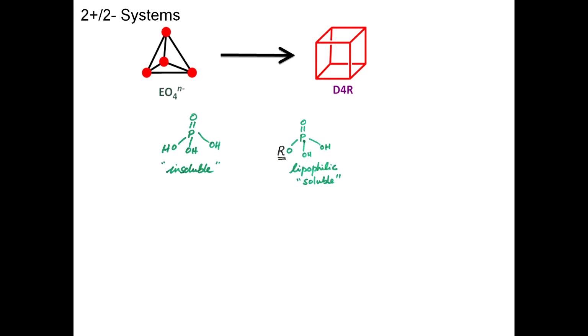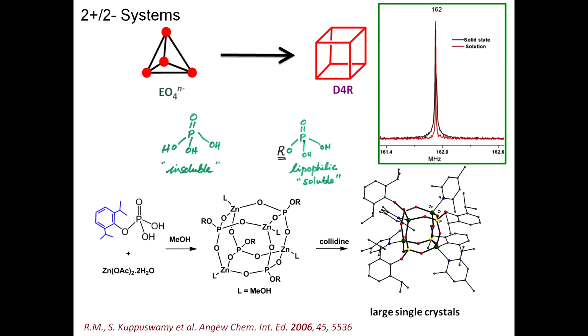So this is what I just talked about. In phosphoric acid, one hydrogen is replaced by an R group, which is insoluble in organic solvents. To make it soluble in organic solvents, I lipophilized it by putting in a 2,6-diisopropyl group. As one would expect, this molecule reacts with a divalent metal ion, namely zinc 2+. The reason I use zinc 2+ is that it's a divalent metal ion which is diamagnetic, so I can do NMR of these samples very easily and know what's going on. I don't have to depend only on single crystal structures.